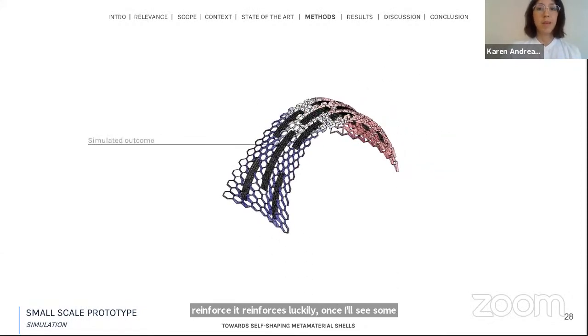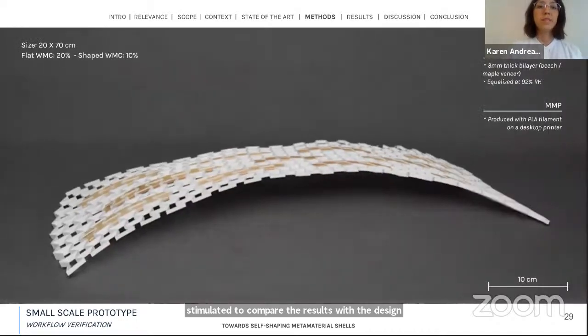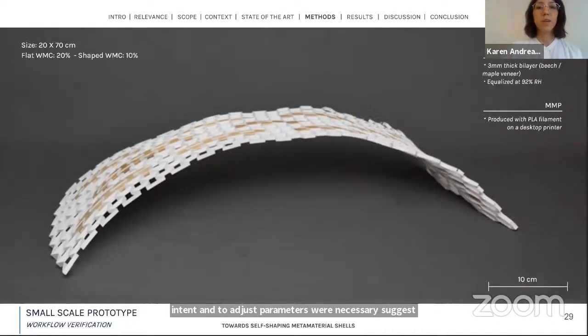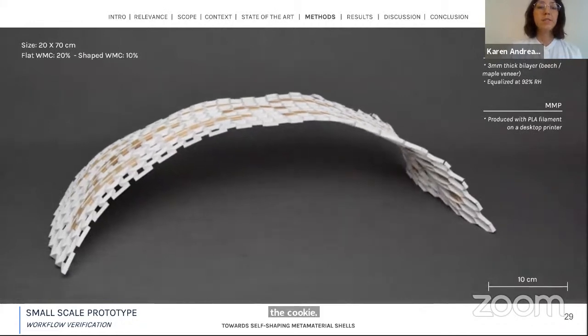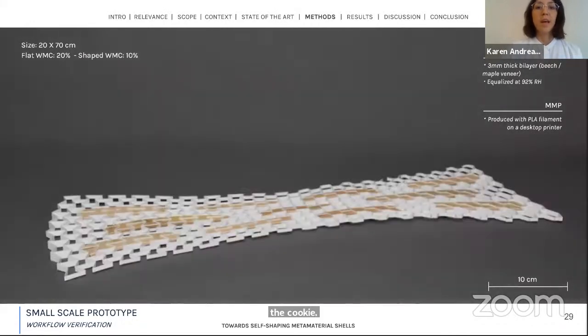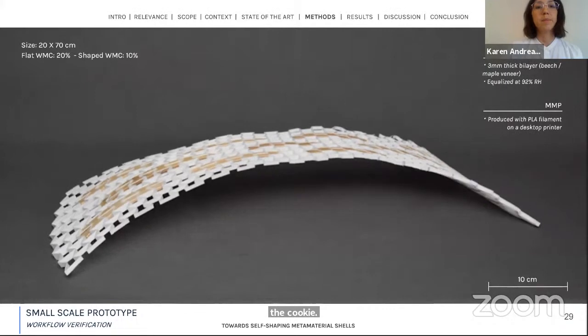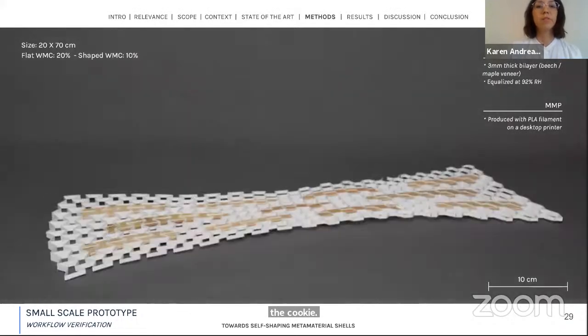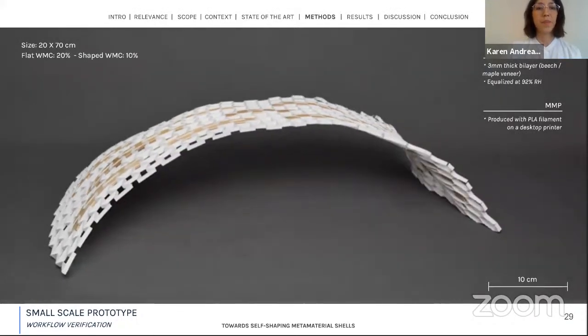Once all system parameters are set, the self-shaping behavior is simulated to compare the results with the design intent and to adjust parameters where necessary. The suggested configuration is then tested with a physical prototype that self-shapes under ambient conditions. The results have shown that the developed simulation tool produces reliable results at this scale.